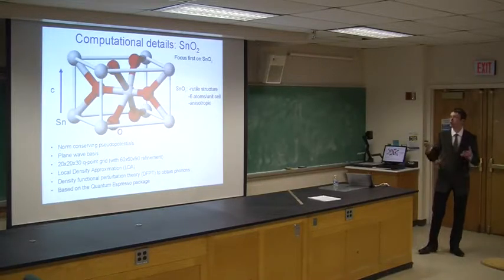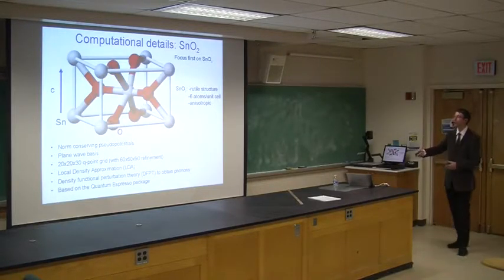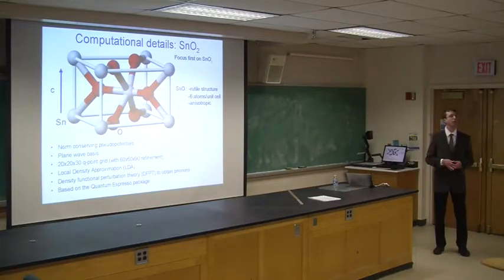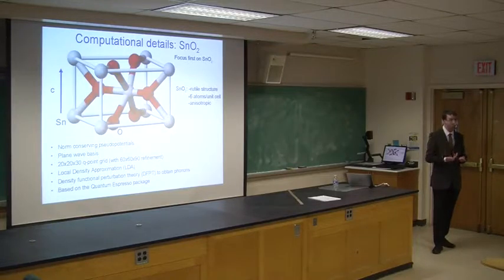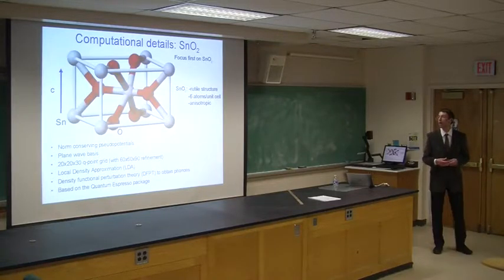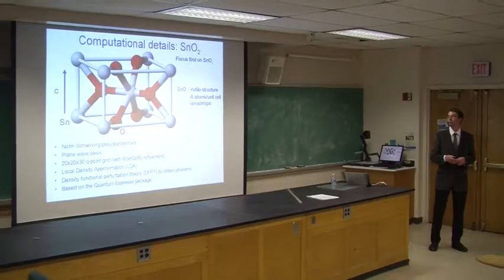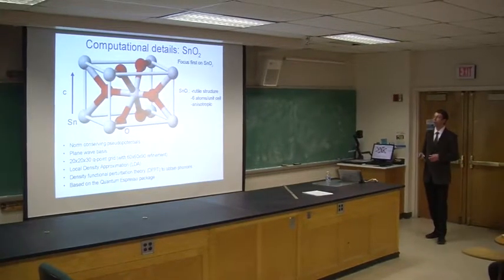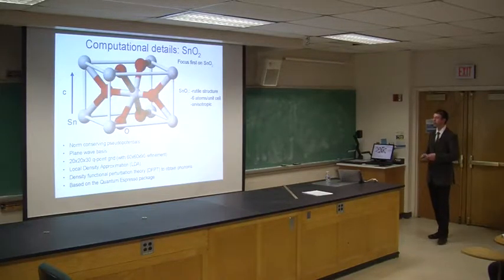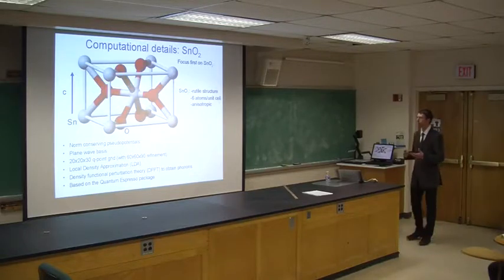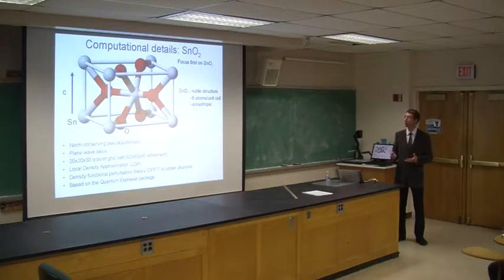And now for those who are more familiar with the technical details, I will be using norm-conserving pseudopotentials in a plane wave basis set. I will use the local density approximation, and everything will be based on the Quantum ESPRESSO package. I will also calculate q points, so the phonons, on a dense grid, and use that to calculate the absorption. So let's have a look at what our results are.